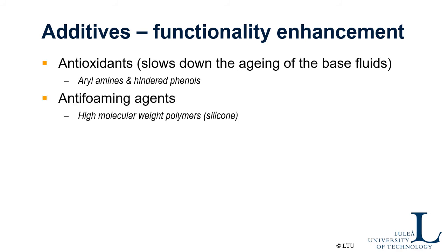You have also anti-foaming agents. The surface tension of the bubbles controls if the bubbles are stable or not. But if you can put something into the lubricant that lowers the surface tension, then the bubbles burst and you don't form as many bubbles. Foaming can be a big problem in a lubricant, especially if you pump it around a lot. So you must normally have this anti-foaming agent.